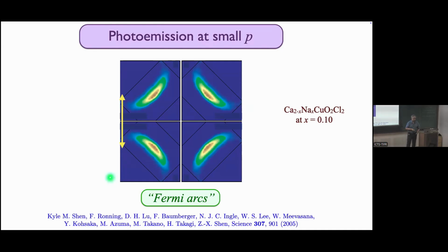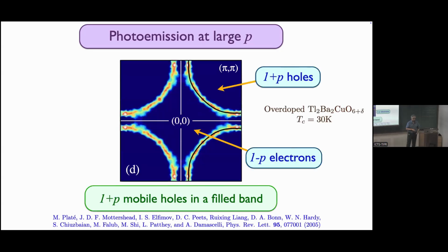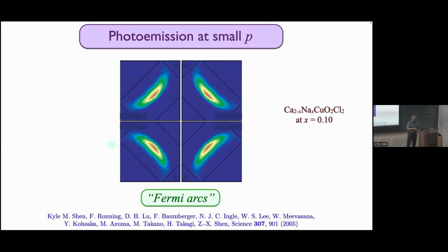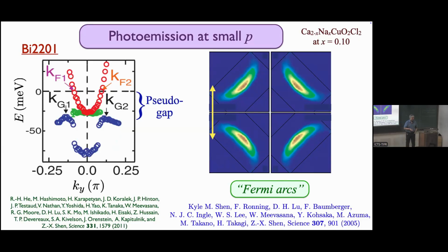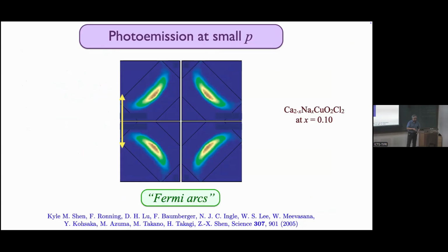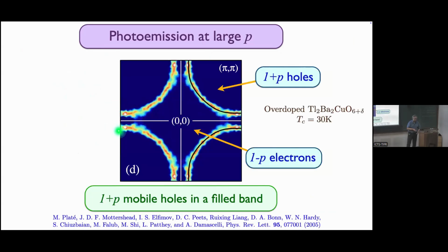So now if you look in this region, the so-called antinodal region, remember here there was a Fermi surface. So now we're going here, where there is a Fermi surface at high doping, but no Fermi surface at low doping, and ask what is the electronic excitation? There clearly is essentially none at zero energy, but at higher energy is what you see as you scan that wave vector. So we're scanning this wave vector along this direction. And if you're on the overdoped side, or at very high temperatures above T star, then you see the red line. And notice the red line crosses zero energy. And that's where the Fermi wave vector is. So these 2 points here, what they call KF1 and KF2, are precisely these points there.